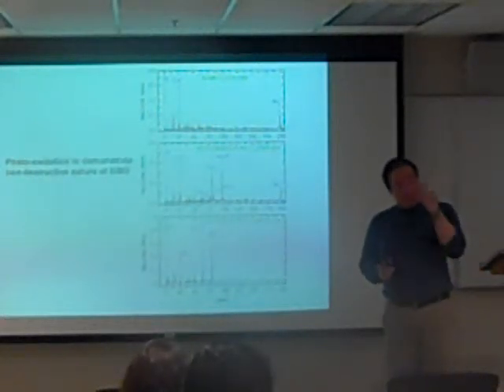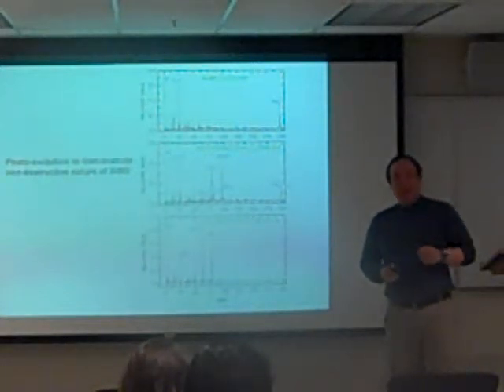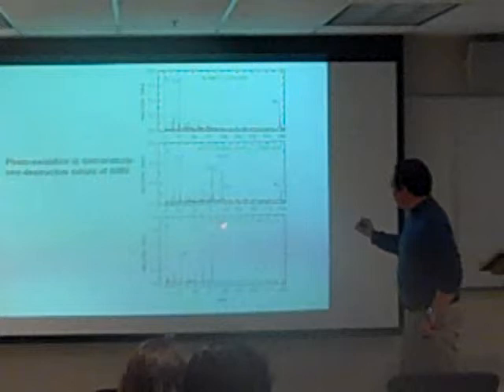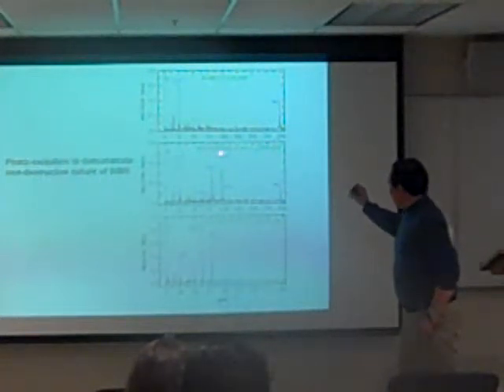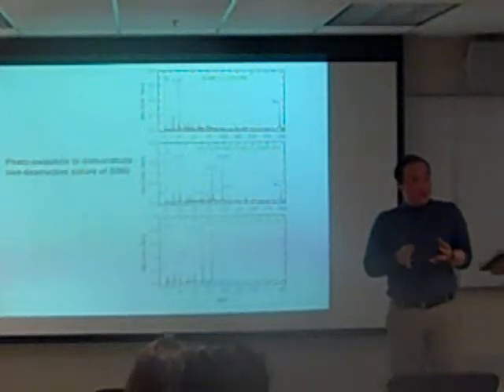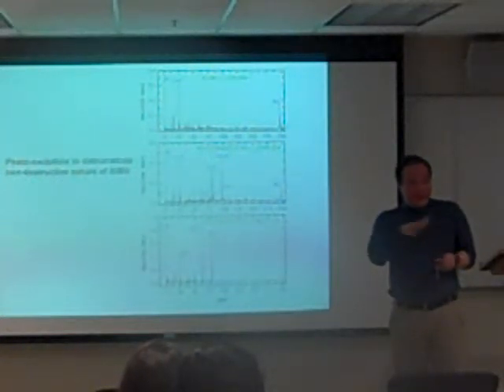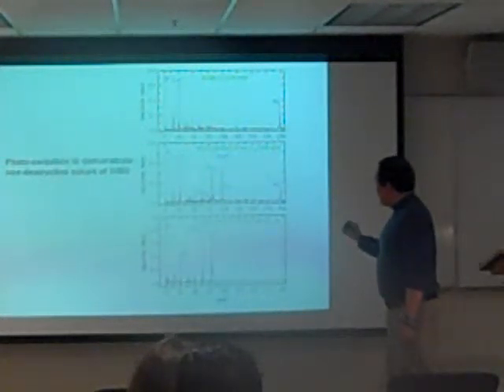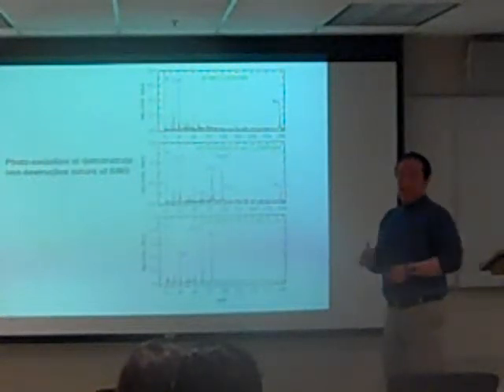One thing that you might ask, as far as some of these surface handling techniques, is whether you might destroy some of the surface during the analysis. So this is a SIMS spectra of the carboxylic acid functionalized SAMs after interaction with phosphate. And this is after this has been photooxidized. So basically, one way to actually destroy the material is to take a UV lamp and shine it on the surface for about 25 minutes or so. That causes the SAMs to be decomposed. And so that's why you see the SO4, SO3. Now it turns out that after the SIMS process, we see no SO4, SO3. So we can be pretty safe that we're not damaging the thing that we're trying to analyze.